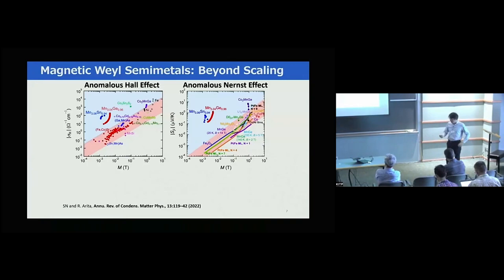One of the important functionalities, if you like, is the response beyond the magnetization scaling of this class of materials. You can see a scaling law of the anomalous Hall or anomalous Nernst effect as a function of magnetization, but these magnetic Weyl semimetals or magnets have two or three orders of magnitude larger enhanced response in comparison with the response you would expect based on the magnetization.